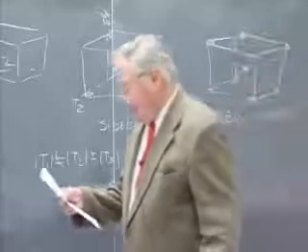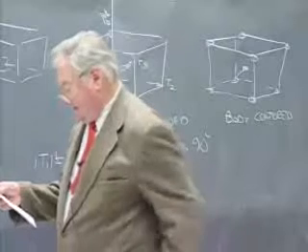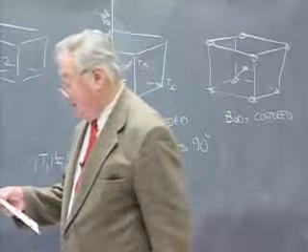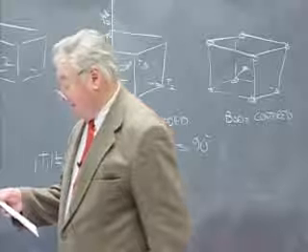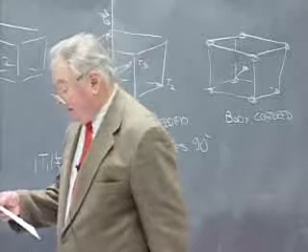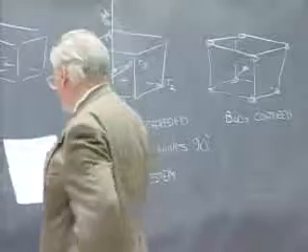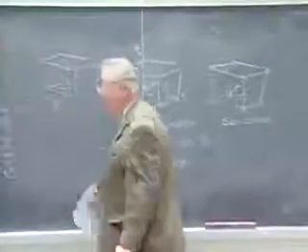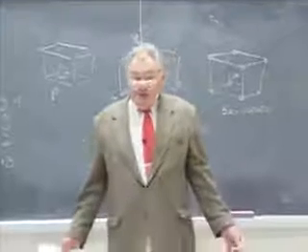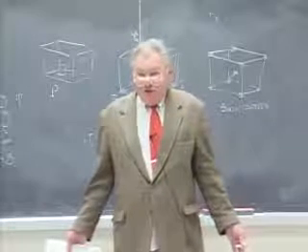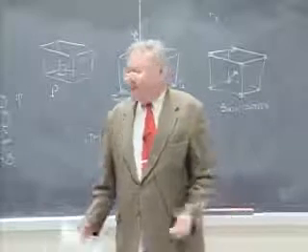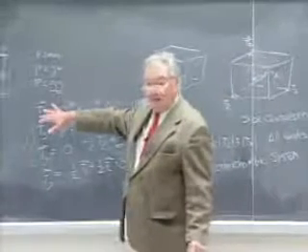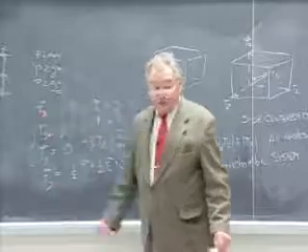So we can get that out of any one of the rectangular groups that has twofold axes and symmetry planes in it. And conversely, take one of these lattices and let the symmetry elements that we found in the plane group extend through them, and you've got a three-dimensional space group. So without emphasizing the fact, as we go along, we're picking up a healthy number of three-dimensional space groups as we go along.